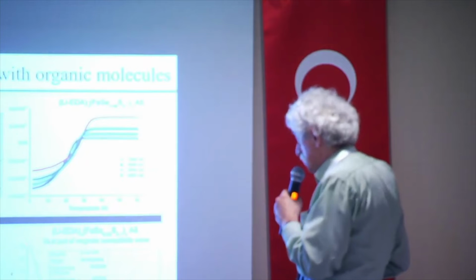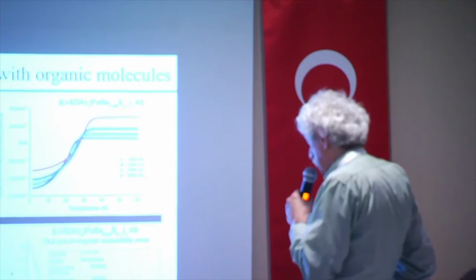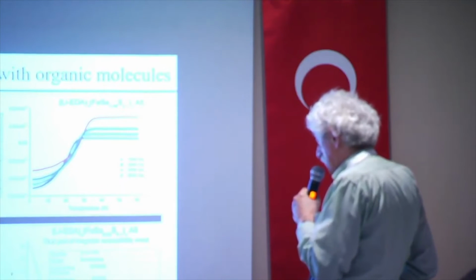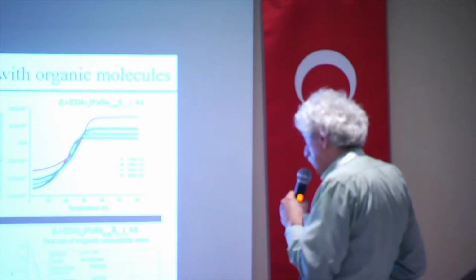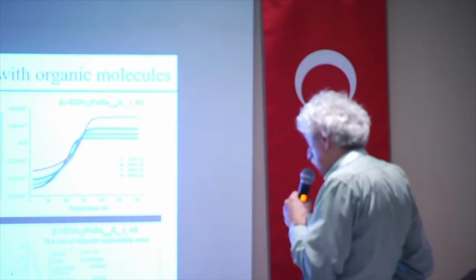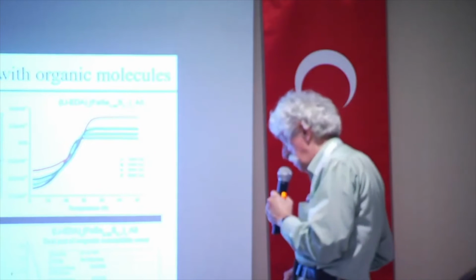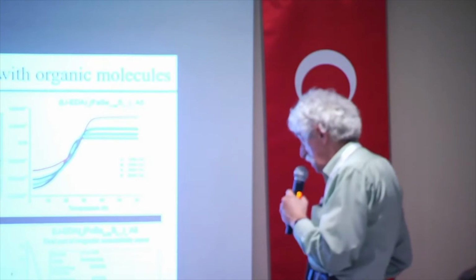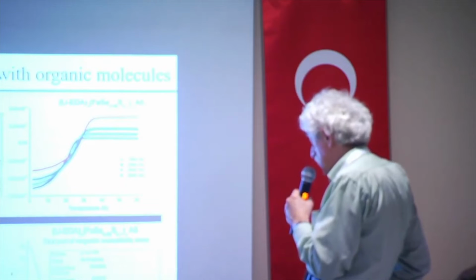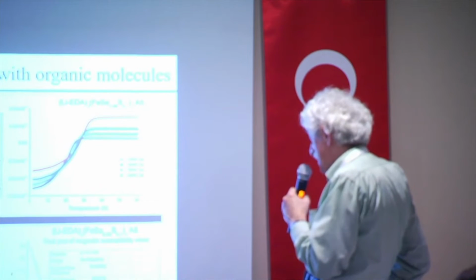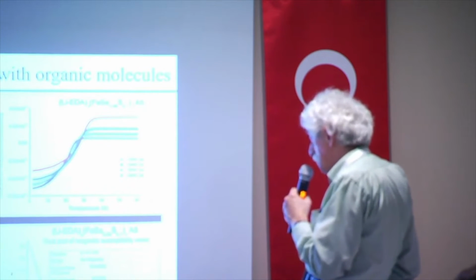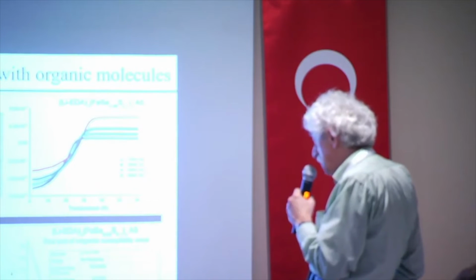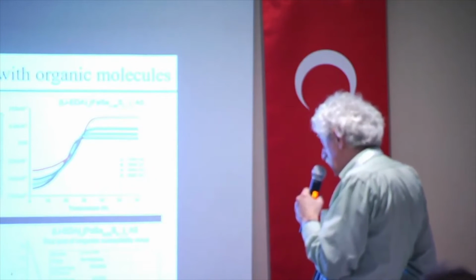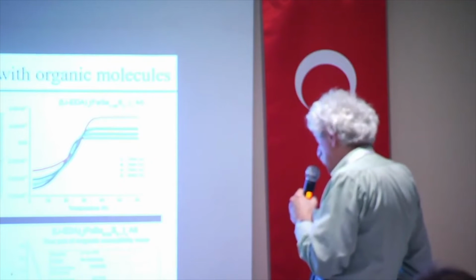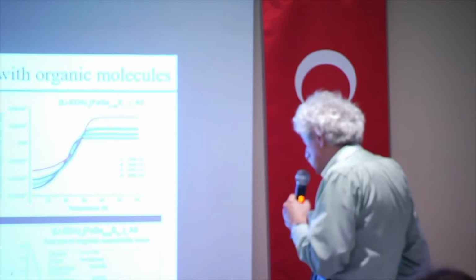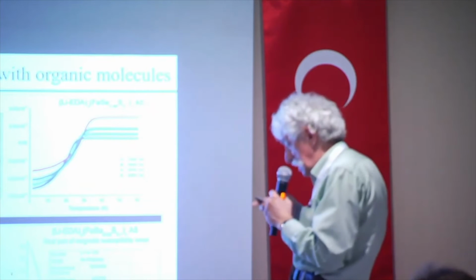And we found for these materials that the upper critical field behaves in such a way. Up to, let's say, 30 Kelvin, we have a very high upper critical field, which is quite similar to rubidium intercalated compounds. However, for higher temperatures, there is a much smaller upper critical field. This upper critical field still exists, but it's much smaller, and this is just somewhere where there is a transition to the non-superconducting state.